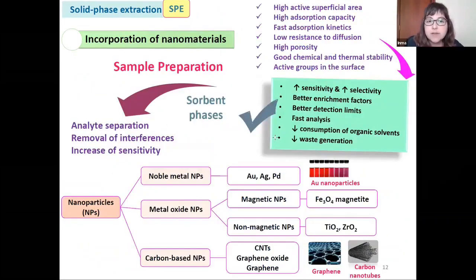Recently, nanomaterials have been used in sample preparation in analytical chemistry, mainly as sorbent phases, due to the different properties in comparison with conventional materials, such as the high active surface area and high adsorption capacity, among other properties, for example, the high porosity and the presence of active groups on the surface of these nanomaterials. The aim is mainly analyte separation, removal of interferences, and increase of the sensitivity. Thus, the incorporation of nanomaterials as sorbent phases allows to increase the sensitivity and selectivity, and as a consequence, the detection limits.